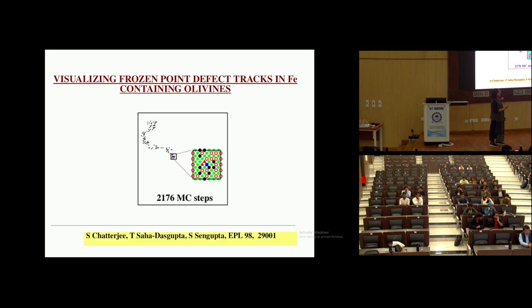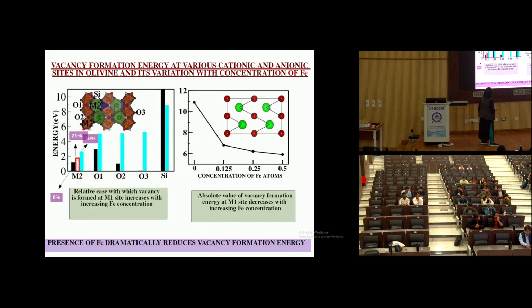So we thought about this problem, and what we found is the following: vacancy is most easily formed at the M1 site. And not only that, in the presence of iron, this vacancy formation energy is hugely reduced. That means if we have iron, the vacancies are much more easily formed. Now, why is that? Any idea? Any wild guess? So, at the M1 site, either I will have magnesium or I will have iron. So that means absence of some magnesium or iron. Right?